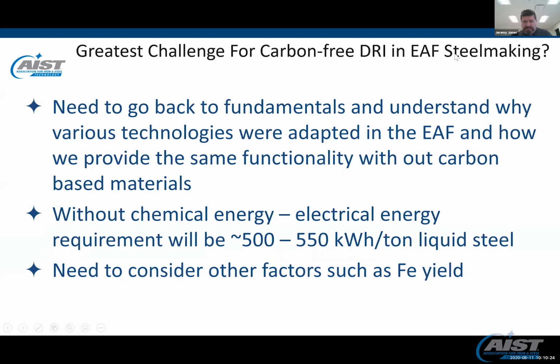Okay, so this morning we had a number of questions ahead of time as sort of a guideline. And one of them was, what are the greatest challenges for carbon-free DRI and EAF steelmaking? Well, in general, as we try to move towards this low carbon footprint steelmaking, what we need to do is return to a lot of the fundamentals and understand why various technologies were adopted and adapted into the EAF. And how do we provide that same functionality without carbon-based materials? So this involves things like the reason why we put burners in an EAF was that we were trying to eliminate cold spots so that the scrap melted in more evenly and we could achieve an efficient endpoint, achieving the temperature and carbon level in the bath at the same time.